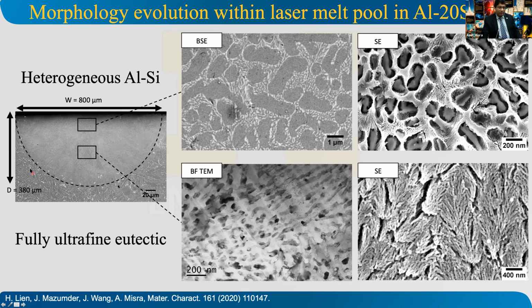And you see at the bottom of the melt pool where the structure did not melt, you can see the textbook style of eutectic structure with silicon flakes. Inside the melt pool, which is everything inside the dotted semicircle, the structure has become so fine that you cannot resolve it at this resolution of 20 micron. But if you blow it up, you can see two different kinds of structures that are shown here.